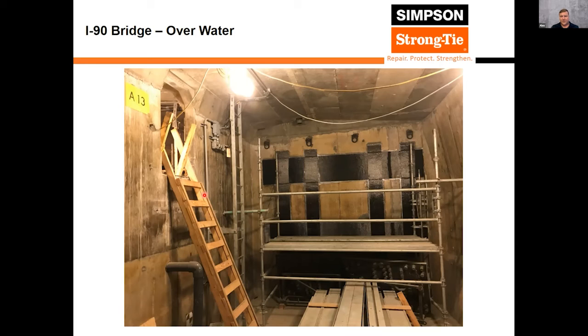So all the FRP in this photo came in through that access hole and was installed down in this confined space. And you can see the horizontal and vertical strips on this wall face are blocking out around these two rectangular sections. And those are the areas that are going to get cut out or cored through for PT strands to string through. So the FRP above and to the sides blocking that out is essentially there to replace any loss of tensile capacity from the rebar that would be in those core locations. So coring through this, we're going to cut a few bars here and there, and the FRP is sized to replace that capacity.